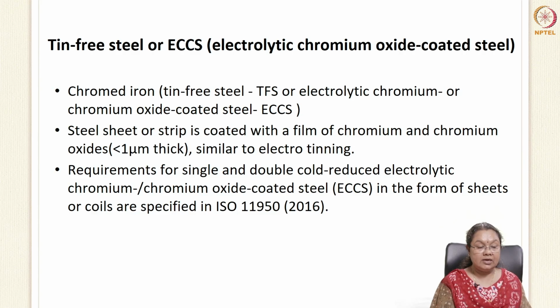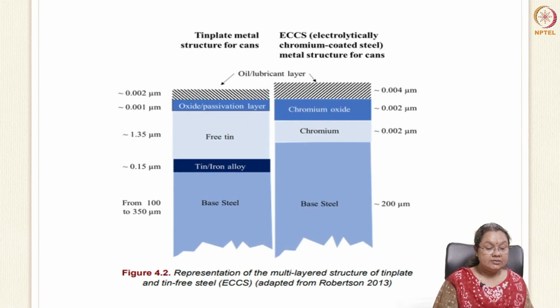So it contains chromium oxide, which has a thickness of less than 1 micron, and the process is similar to electro tinning. The requirements for ECCS, that is single or double cold reduced electrolytic chromium oxide coated steel, are given in ISO 11950. The specifications are given for both sheets and coils there. So if you look at the figure here, it is a multi-layered structure of tin plate and tin-free steel. In this, you can see that the thickness of the base material can range between 100 to 350 microns. And over the base material, a tin coating is given, which is not given in the tin-free steel. There's a tin coating or tin alloy, over which there's a free tin, which has a thickness of 1.35 microns. And over this, the passivation layer is put.